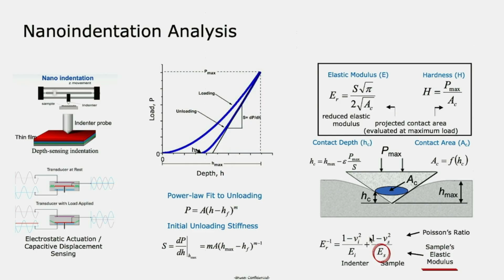So we can use this curve to apply the mechanical model from Oliver and Pharr, that was developed in 1992. Then we can calculate the elastic modulus and the hardness here. The elastic modulus is defined by the contact stiffness divided by the area. Contact stiffness is defined by the slope of the unloading curve, and the contact depth also comes from the Oliver-Pharr model. And hardness is quite similar to Vickers hardness.